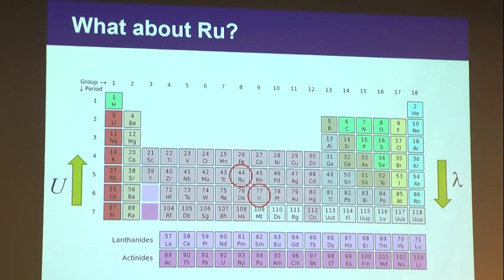Okay, so with this in the backdrop, we were thinking about our next move when we were studying this sodium iridium oxide. Instead of trying to come up with a different structure, let's stay with the honeycomb lattice structure, but think about switching the main metal ion. So instead of iridium, what if we use ruthenium? Ruthenium can have a ruthenium 3+, which is a 4d electron system. But of course, the worry is that we need a large spin-orbit coupling, and the way to get large spin-orbit coupling is going down in the periodic table rather than going up. So what can we do about this one?